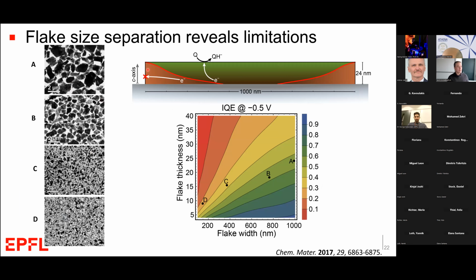If we imagine the cross-section of a flake like this, light can be absorbed at any part of this flake, generating electrons, which we want to travel to the basal plane to reduce, for example, the protons to hydrogen. However, if those photogenerated charge carriers are generated too close to the edge where recombination can occur, then they'll more likely be transported there and undergo recombination. So based on our experimental results and our drift diffusion model, we can predict the quantum efficiency depending on the flake size, either the thickness or the flake width.